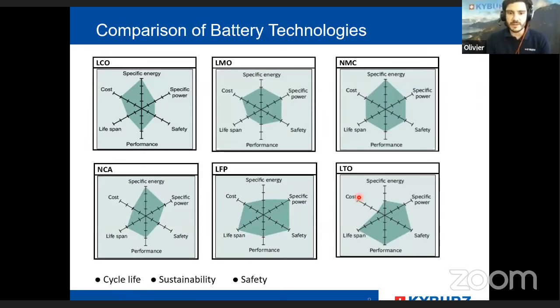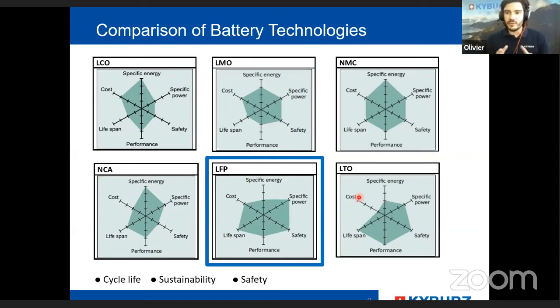Which chemistry do we use? We chose LFP cells for three reasons. The cycle life is much higher than NMC or NCA. Also, for the environment it's better to use LFP because we don't have any cobalt or other rare materials. And one of the main reasons was safety. If we have a short circuit inside the battery, the valve opens and smoke comes out, but the temperature reaches 200 to 250 degrees and it doesn't burn. Therefore we chose LFP cells.